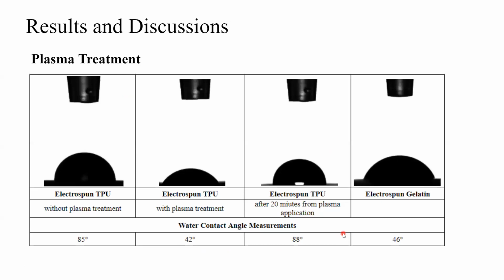Here we can see the contact angle measurements. First of all, contact angle measurement of electrospun TPU mat without plasma treatment shows 85 degrees. After the plasma treatment, its contact angle decreases to 42 degrees, and it shows us that it becomes more hydrophilic.